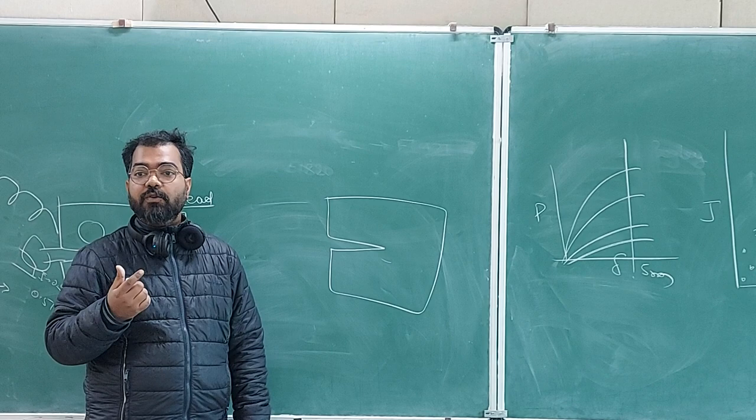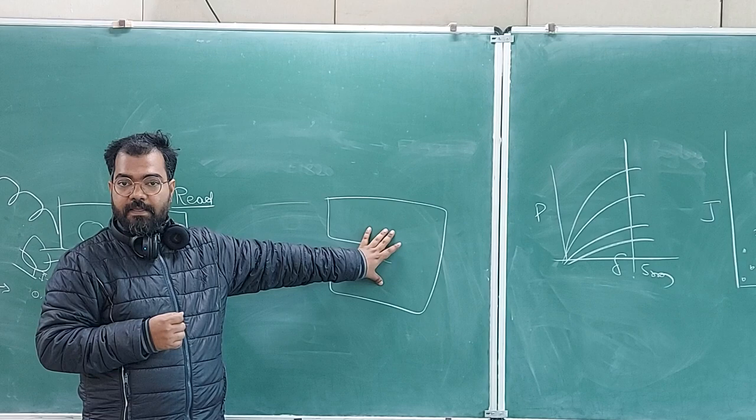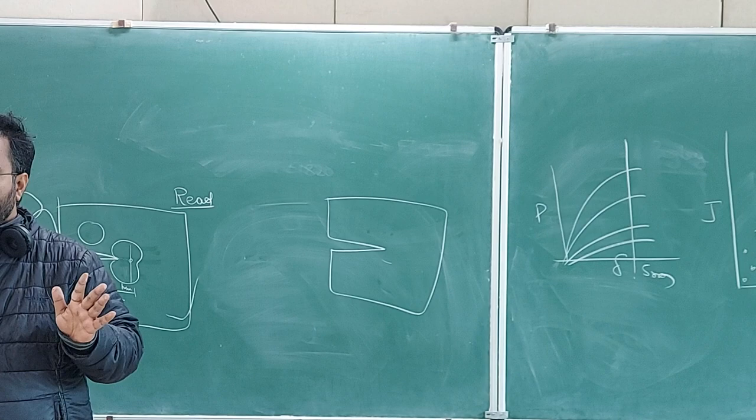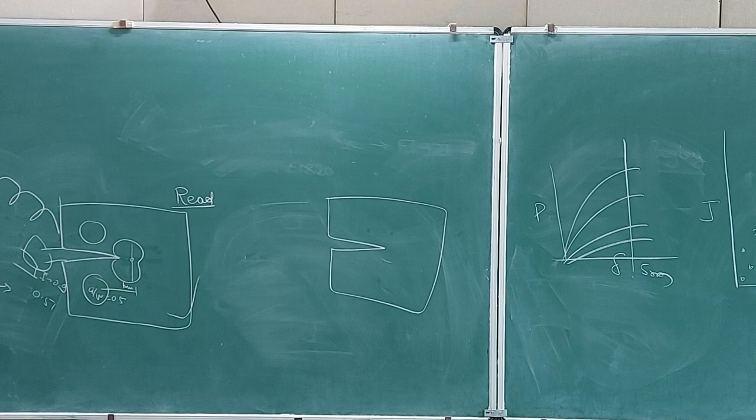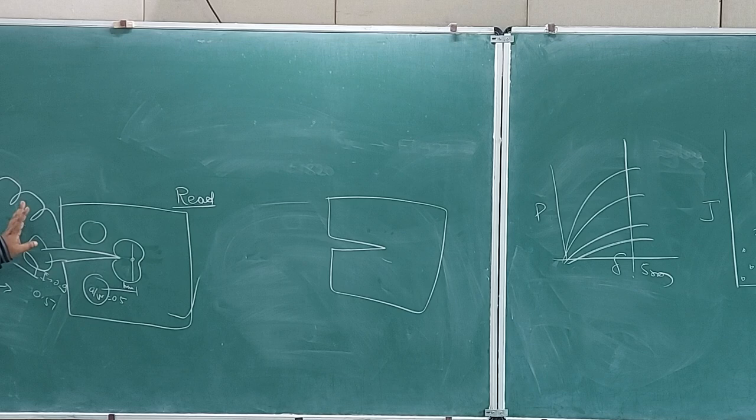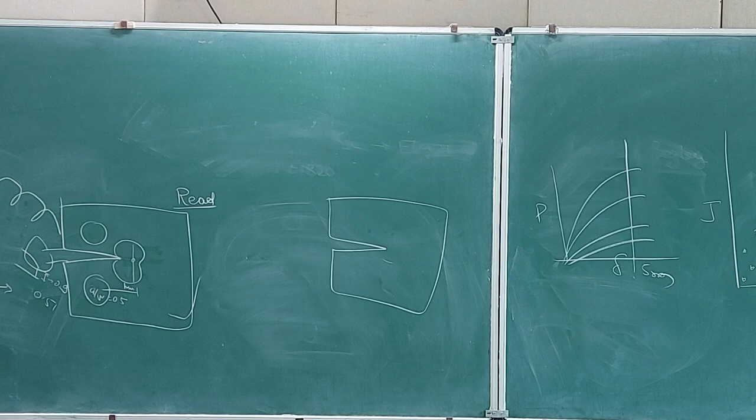But if there is any, how do we ensure? So you stop the test after 5 millimeter of displacement. And after that, what do you do? You do fatigue again to break the whole sample. Why are you doing fatigue? Even in this case, when you stop the test here, you are supposed to break it by fatigue. Why fatigue? Because you want to measure how much crack growth has happened while the test.